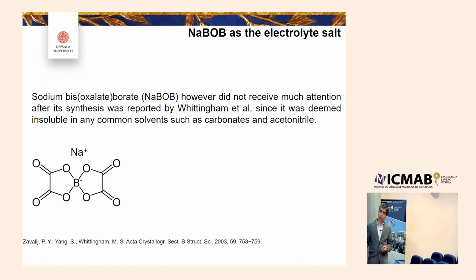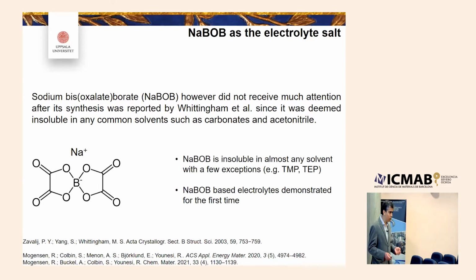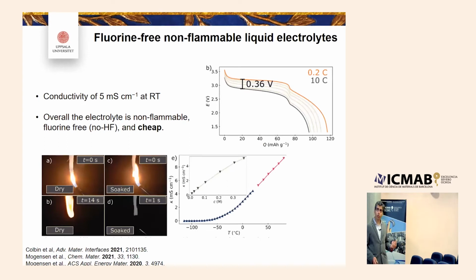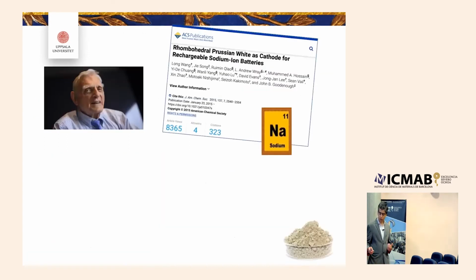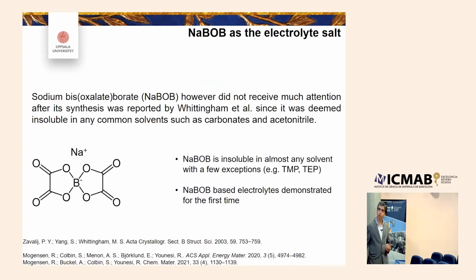We found that the reason is sodium BOB is very much insoluble in common solvents like ethers, carbonates, and so on. Then, largely by accident, we were lucky to find out sodium BOB is actually soluble in phosphate-based solvents, including TMP, TEP, and so on. It is also soluble in NMP, but NMP of course is not that interesting a solvent in terms of toxicity.